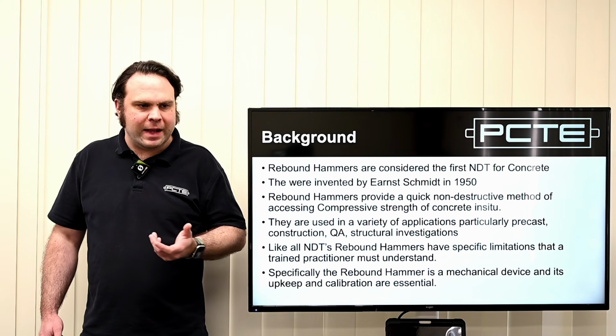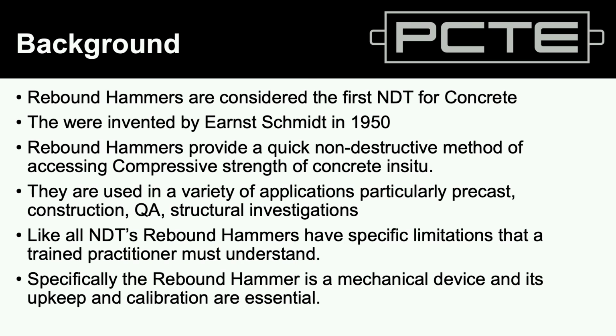The rebound hammer is one of the very first non-destructive tests available for concrete, and it is used primarily for relative strength of concrete in situ and comparison between different concrete. There are limits to Schmidt hammers that I'm going to go into, but probably the biggest limit to keep in mind as you work is that they are a relative strength, and the relationships that are built into them from the manufacturer may not be a good match to your materials on site. So that's probably the biggest lesson: if you just take it and get an MPa, sure, but it's not going to be the most practical use of that tool.